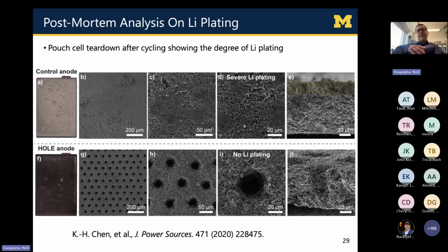We then take the batteries, we tear them apart, and we look inside. And what we can see is that the control anode, as I showed before, has a lot of this lithium plating all over the surface. The entire surface of the electrode is covered with plated lithium, and you can see in the cross-section this kind of thick, mossy lithium layer that has plated on the surface.